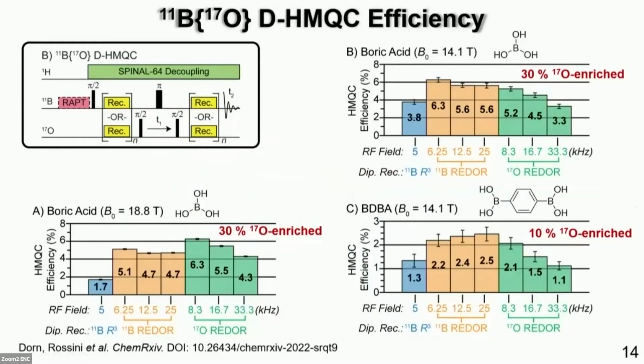We then determined the boron-oxygen D-HMQC efficiencies by comparing a 1D HMQC to that of a boron spin echo, where we kept the echo time to match that of our recoupling time to normalize for transverse relaxation. What we can see for boric acid that is 30% oxygen labeled, we're getting efficiencies of around 6%, and for benzene diboronic acid, this drops to around 2% because it's only 10% oxygen labeled. Now, what is important here is that you see that the overall efficiency doesn't really change too much whether you apply the recoupling on the boron or the oxygen channel, thus demonstrating the general applicability of these type of experiments for many different spin systems. And the choice of recoupling is likely going to be sample dependent.